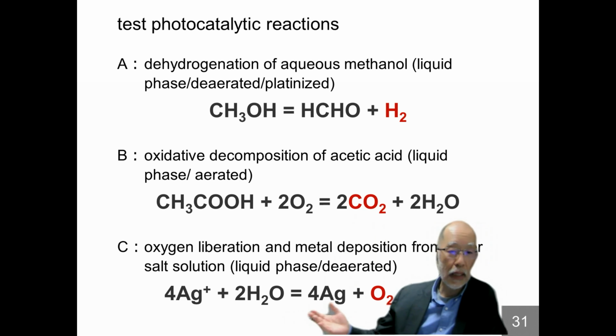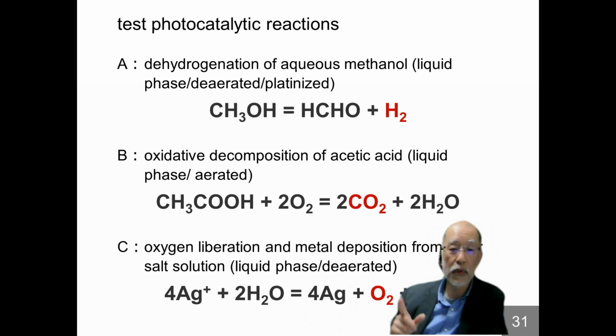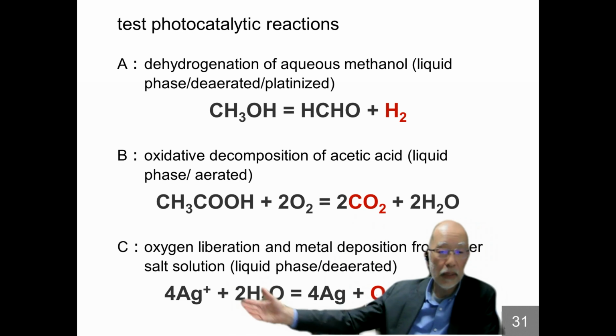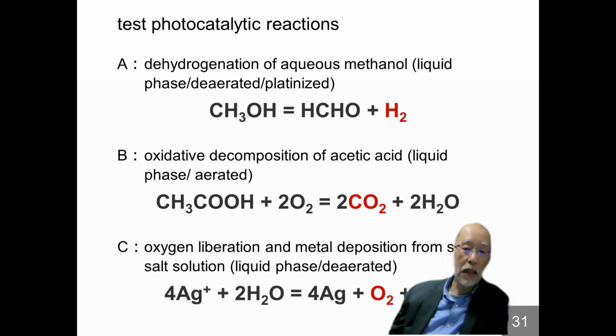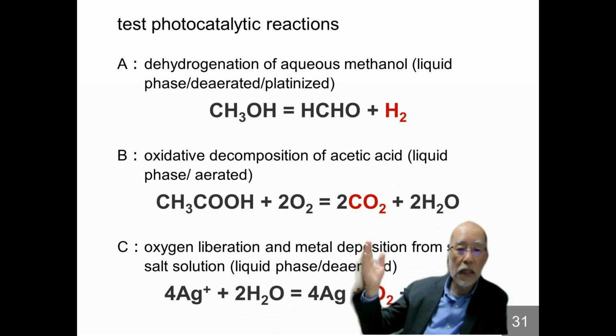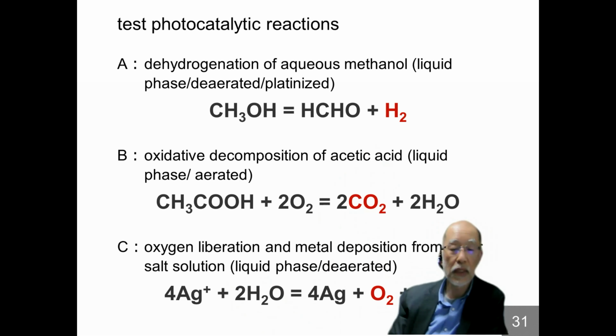And the last reaction is oxygen evolution. That is the model reaction of water photolysis. By using silver ion as an electron acceptor, oxygen is evolved from water by oxidation. So H2, carbon dioxide and O2 are detected to evaluate the photocatalytic activity of the samples.